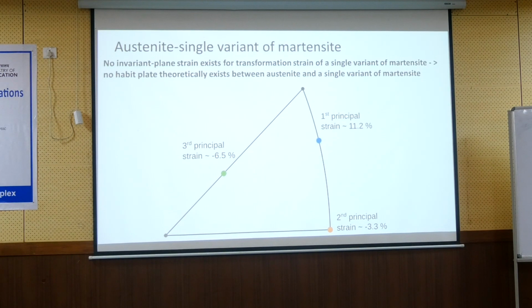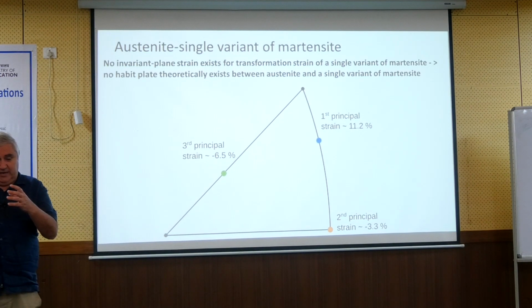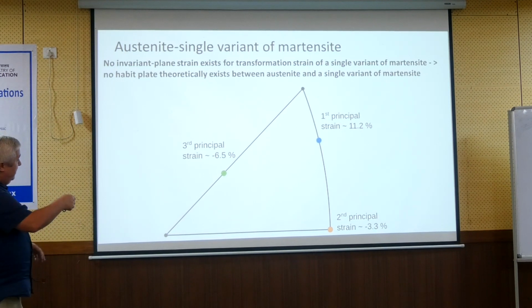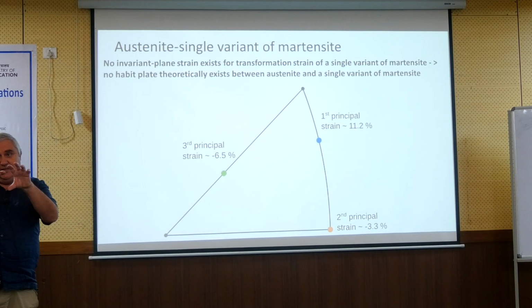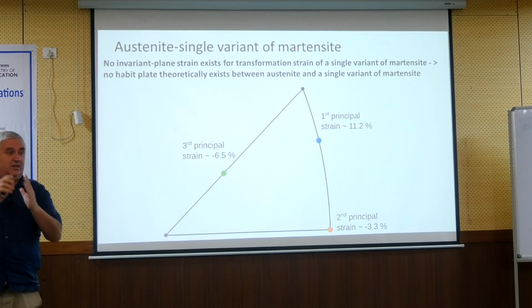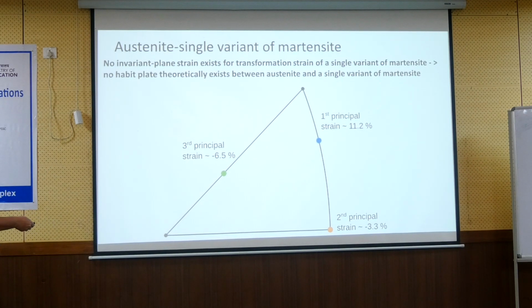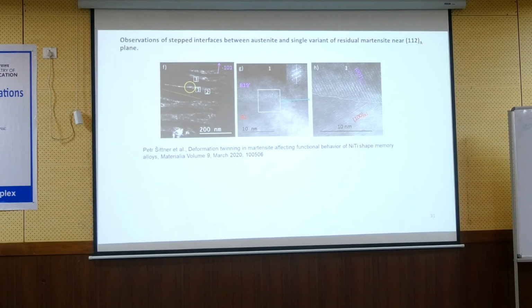This is when it is plotted with respect to the austenite. So with respect to the austenite phase, I have here this and this, which during the particularly this third principal strain and first, this very large mismatch is basically already taken care by the Bain strain. So along this direction, the martensite is oriented in such a way that there is no strain mismatch. The only problem remains with this second principal strain around about 3%, but 3% it's a lot for elasticity. Elasticity can make 0.5%, not 3%. So but when we look into the, so we still have this 2% which no one knows how to explain.